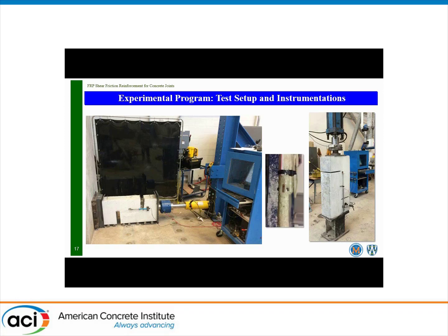The main instrumentation was just 2 strain gauges at the middle of the bar, exactly at the level of the interface between the 2 specimens, as the critical point for stresses and strains as indicated by previous studies in steel reinforcement, as well as each specimen provided with 2 long LVDTs on each side to measure the relative slip between specimens.